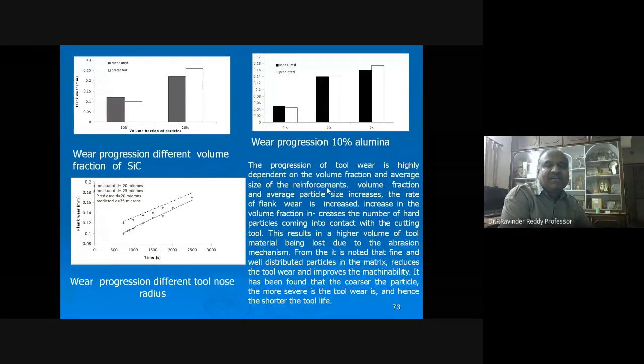It is noted that fine and well-distributed particles in the matrix reduce the tool wear and improve the machinability. It has been found that the coarser the particle, the more severe is the tool wear, and hence the lower is the tool life.